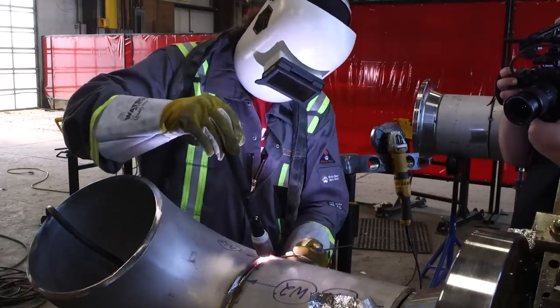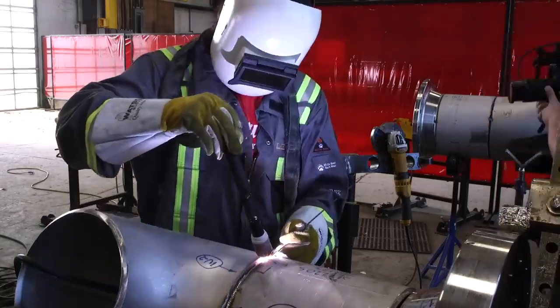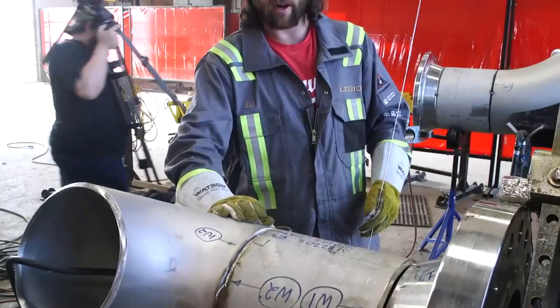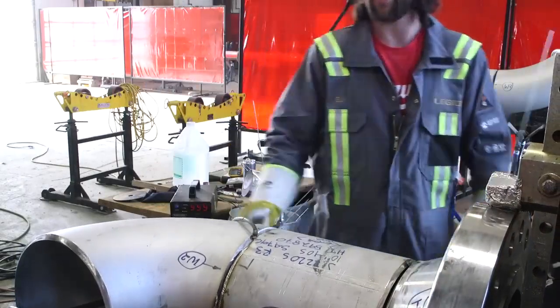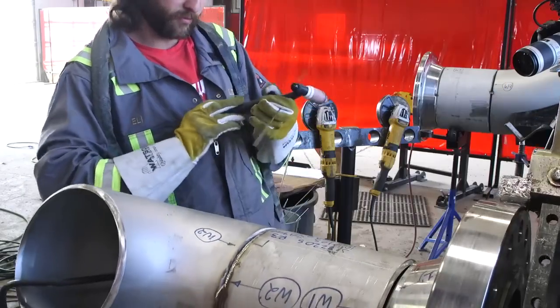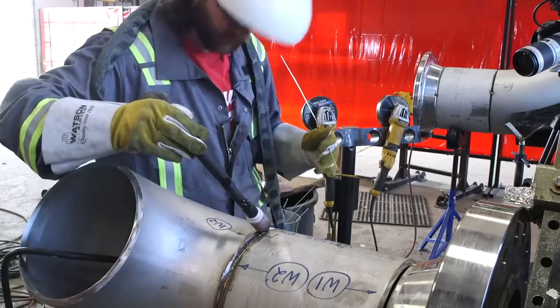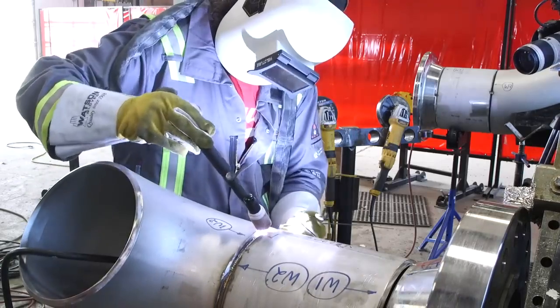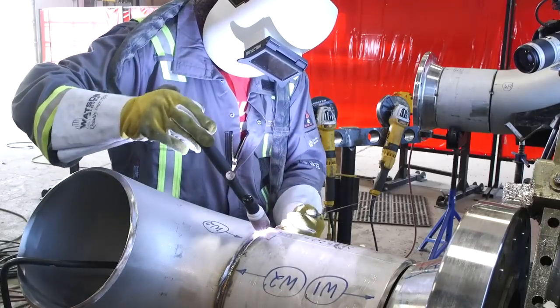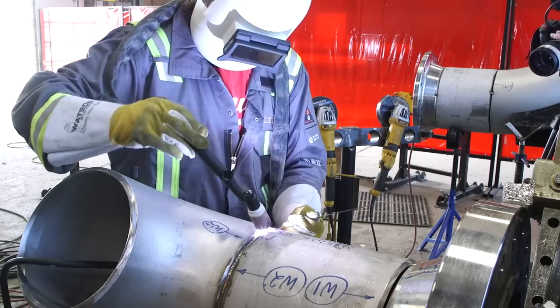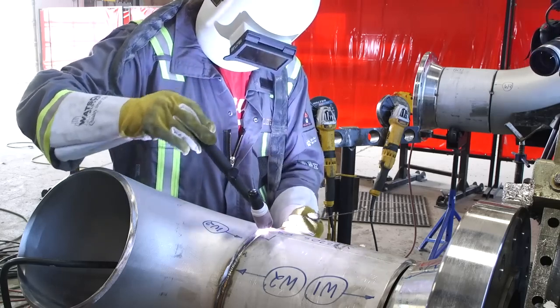The duplex, the max interpass temperature, according to the welding procedures, is 300 degrees Fahrenheit. So as you can see, Eli has a very nice purge going. He would have started at about around 25. It would have been a good purge. And then when you have the root pass in, and the root pass is fully completely finished, the parts per million of oxygen on the hot pass drops down to less than 11 parts per million.